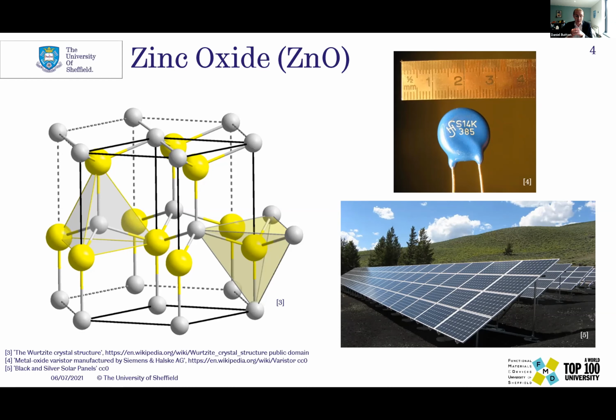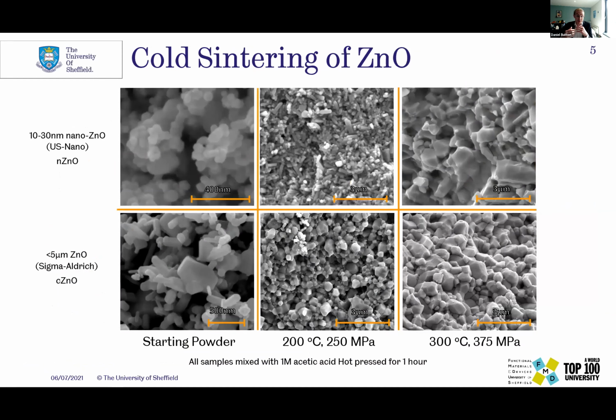So if you go to the next slide, please. This is some of the work that I've been working on. Zinc oxide has been cold sintered. There's quite a lot of literature on it, but we're now getting down into the science of how we're cold sintering it, and the effects of things like powder size. The top row is a very small 10 to 30 nanometer powder that we used, and the bottom is a far more general, out of the pot Sigma Aldrich less than 5 micron powder that had a very wide grain size, and the effects of cold sintering.